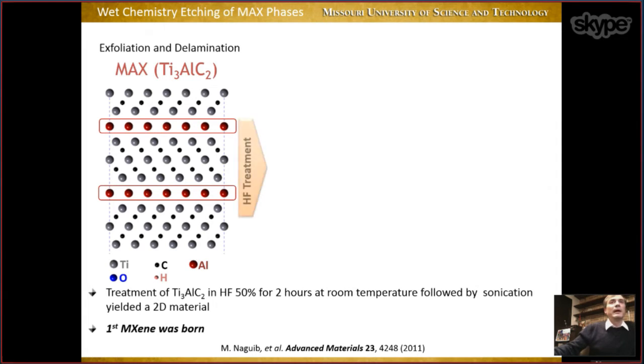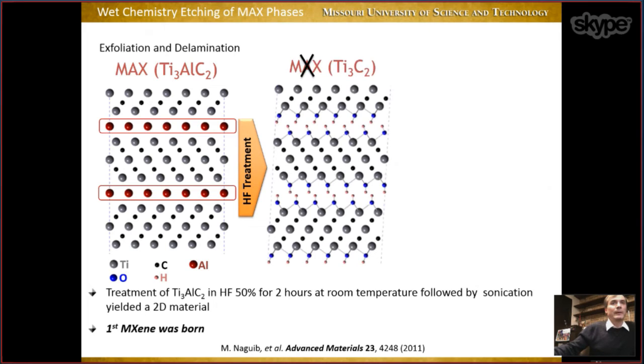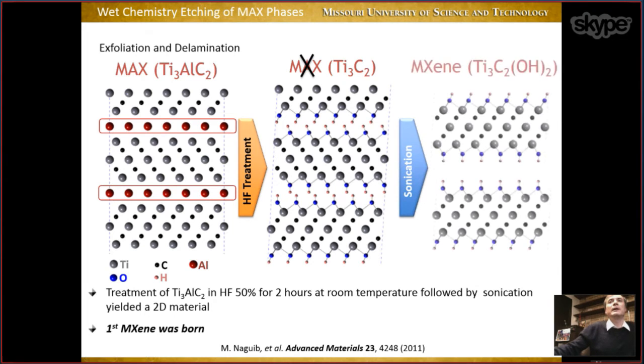So we took them and treated them with HF. When we treat them with HF, we basically remove the aluminum, the A element layer. And what we end up with are just MX layers. This is what gives the name to this material, MXene. So we start with MAX phases, we cross out the A because we remove it, we have MX, and then to emphasize that this is a 2D material, we add the ending -ene. So the name is MXene, in analogy to graphite.